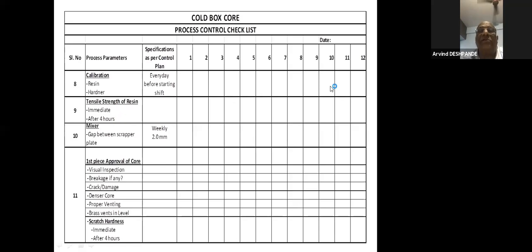Then comes the mixer. The gap between the scraper plate, blade and scraper should be 2 mm, and it has to be checked weekly. Normally, just like in the machine shop, first piece approval of the core has to be done: visual inspection for breakage, crack, damage, Denser Core, proper venting as per the control plan or SPS, standard processing.